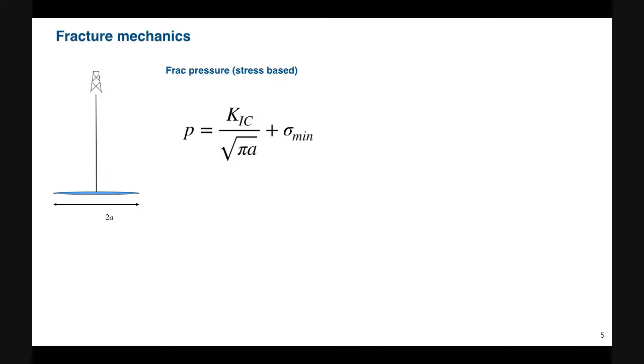Okay, so this equation gives us the frac pressure required to propagate this line crack with half length A. First we need to overcome the minimum stress, and then we have this extra bit. And what is this extra bit? It has the critical stress intensity factor in the numerator, which is a material property, divided by the square root of pi A. This is from the geometry.